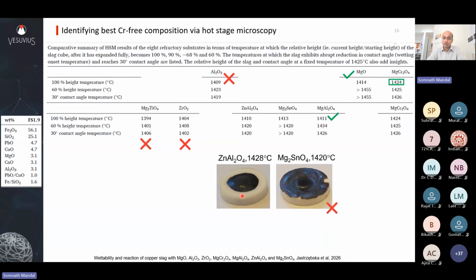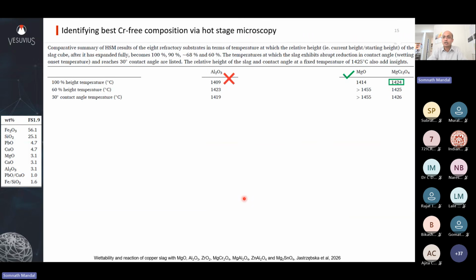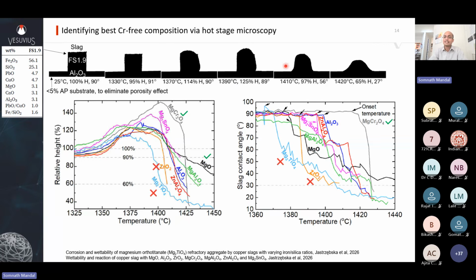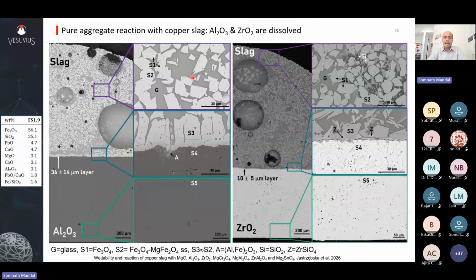Now we also did cross section of these materials. So basically we took a portion from this and did a SEM analysis. So this is what you see in here. The slag, which is fayalitic slag, with this composition, you see a lot of Fe3O4 and Fe3O4-MgFe2O4 solid solution in the slag, these grains, and then you have a lot of glass. And then you see the direct dissolution of your alumina into the slag, and sometimes it forms these Al2O3-Fe2O3 solid solution in the interface. The zirconia, again, it gets dissolved and forms zircon in reaction with the fayalitic iron silicate slag, and this is not good. You don't want direct dissolution of your refractory, and due to this, sometimes silica is precipitated.